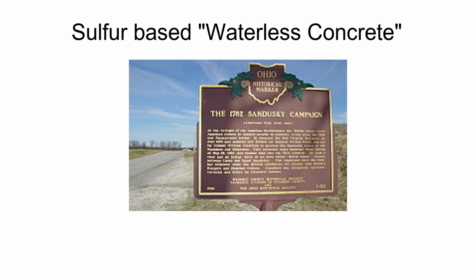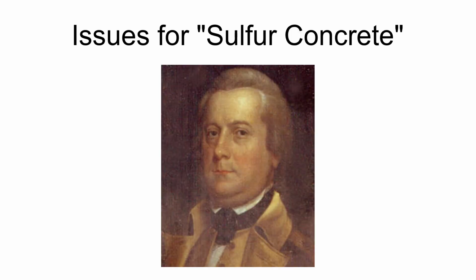with an average compressive strength of 33.8 MPa and tensile strength of 3.7 MPa. Addition of 2% metal fiber increased the compressive strength to 43.0 MPa. Addition of silica also increases the strength of the concrete. This sulfur concrete could be of a special value for dust minimization, for instance to create a launching pad for rockets leaving the moon. It provides less protection from cosmic radiation, so walls would need to be thicker than concrete walls. The water in concrete is an especially good absorber of cosmic radiation.